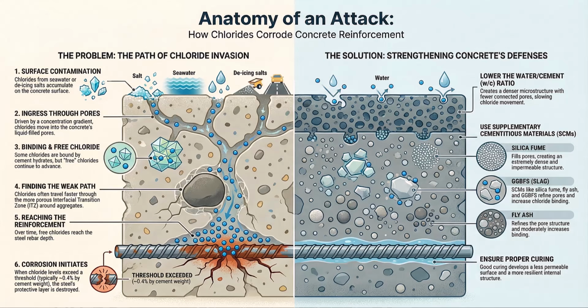And finally, we have performance testing. Major projects don't just check the paperwork, they test the material's actual resistance. The Rapid Chloride Permeability Test, or RCPT, must yield very low charge values, 1,000 coulombs or less. And they test the diffusion directly. They do. They mandate a direct diffusion coefficient target, often written as D_nssm, of less than or equal to 2.0 times 10 to the minus 12.